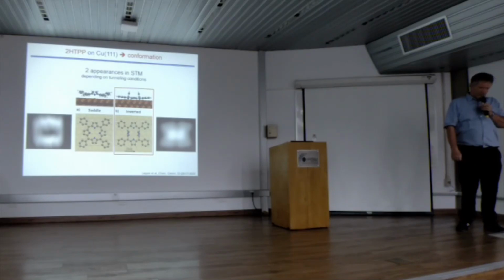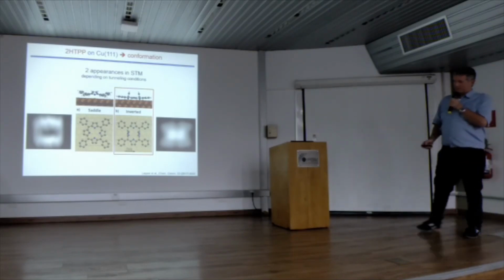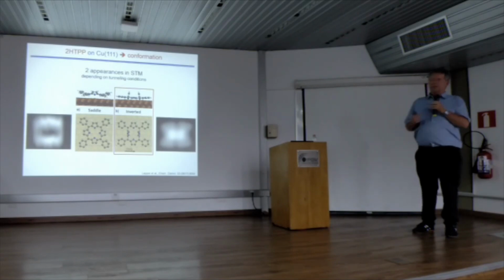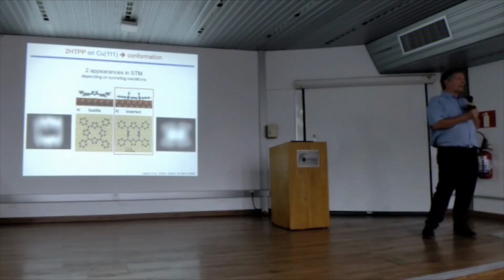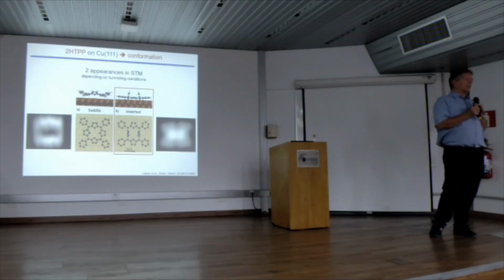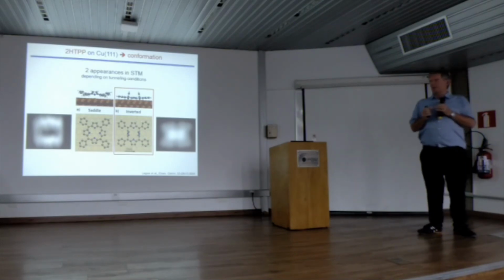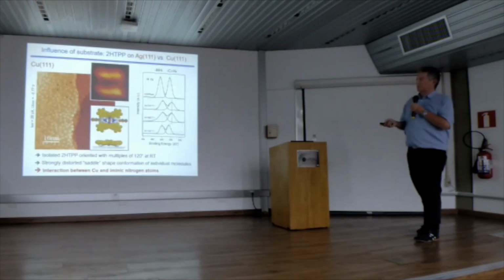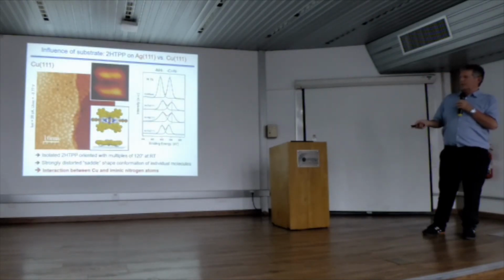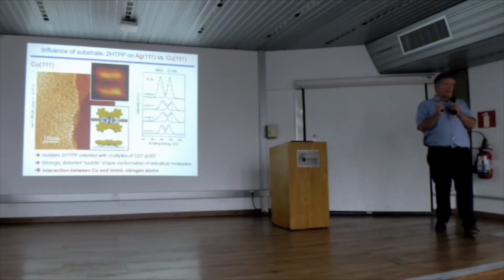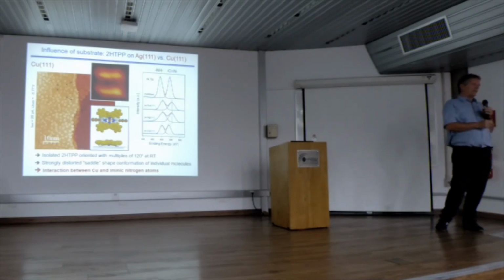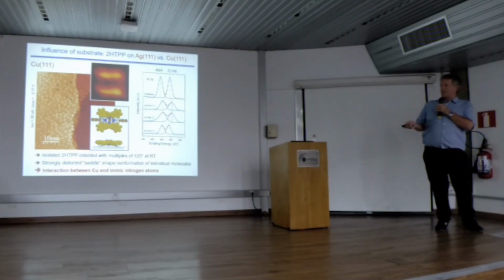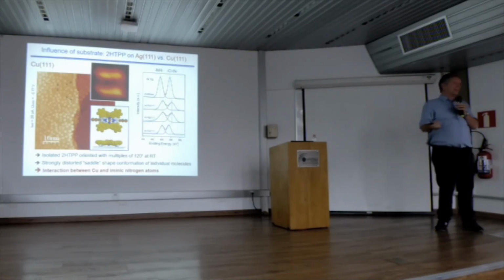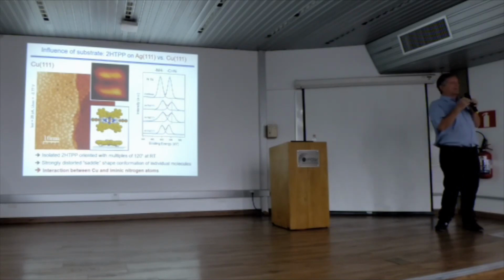Actually, it turns out that we did iron and cobalt. Iron is extremely reactive. It immediately reacts at room temperature. At the beginning we thought that, because of this copper surface, you have this very strong interaction, and this would be the precursor for the metallation reaction. But it turns out that at room temperature, the activation barrier is not overcome. Obviously, this is a structure that is energetically so stable that the metallation is not so attractive.